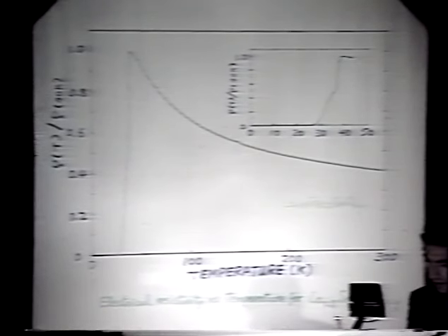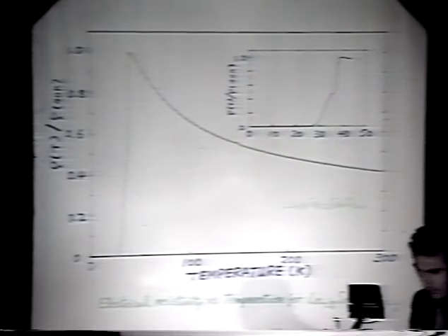Let me show you some of our latest findings. Here we show the temperature dependence of the resistivity for a single phase La1.8Sr0.2CuO4. We found a very sharp resistivity transition with onset at 38 Kelvin, but a foot develops in the middle of the transition, and the resistivity goes to zero only at about 28 Kelvin.